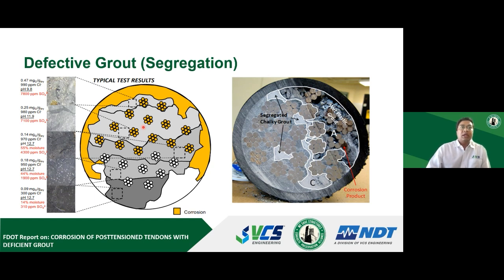What it results in is incompatible material in the same duct. Even if the duct is completely full of grout, you can have segregation, and that will result in an incompatible mix where the top tendons are exposed to a very powdery grout, or a grout of higher water to cement ratio.